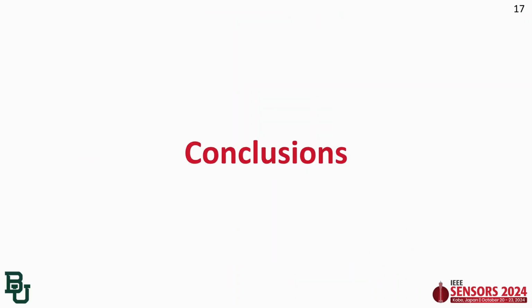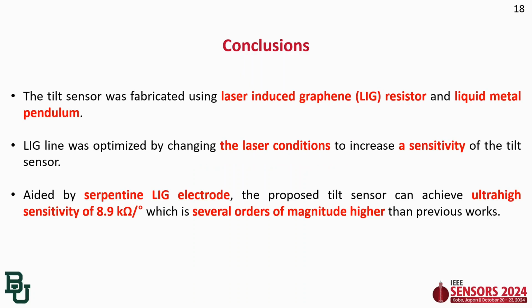In conclusion, the tilt sensor was fabricated using a laser-induced graphene LIG resistor and a liquid metal pendulum. The LIG line was optimized by changing the laser condition to increase the sensitivity of the tilt sensor. Aided by the serpentine LIG electrode, the proposed tilt sensor can achieve an ultra-high sensitivity of 8.9 kilo ohm per degree, which is several orders of magnitude higher than previous work.